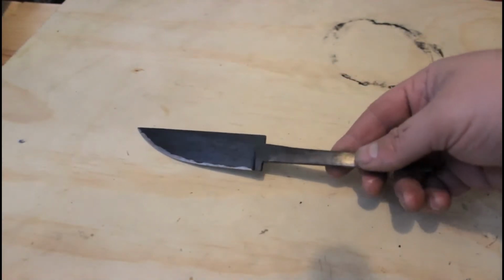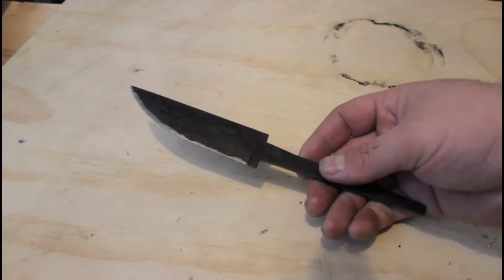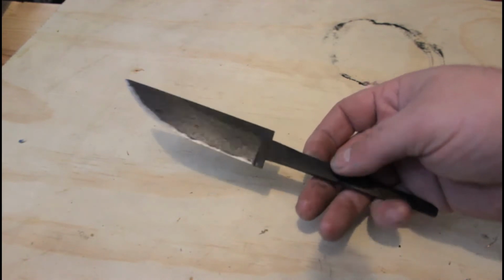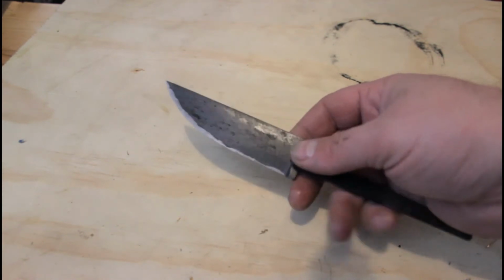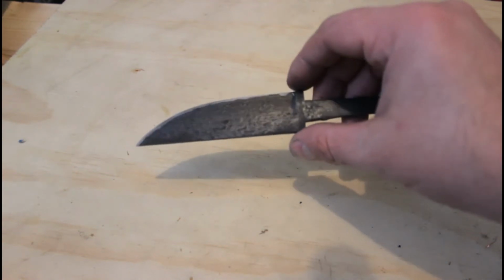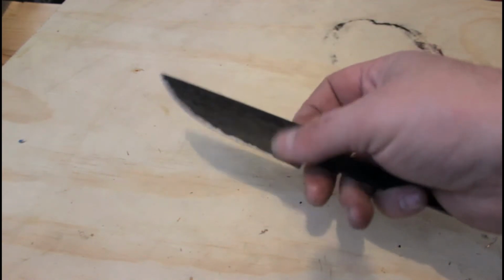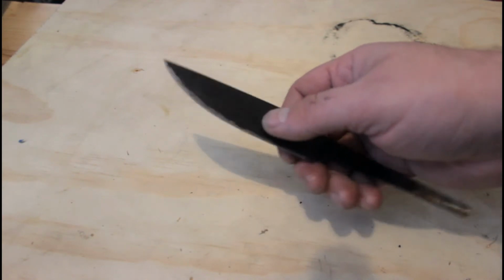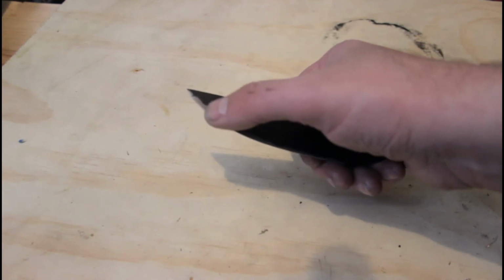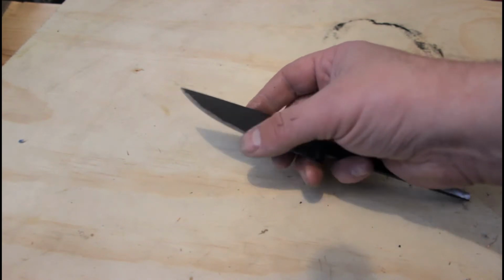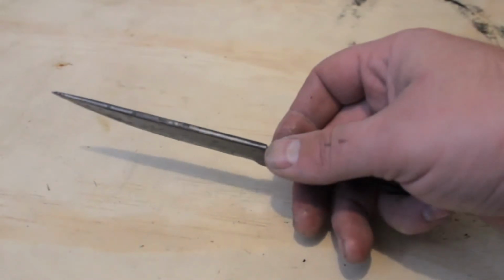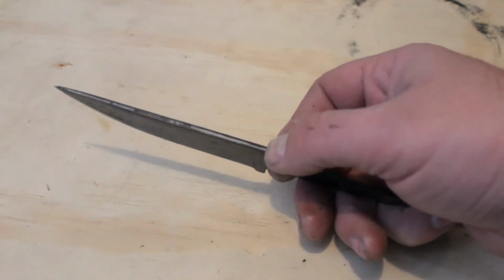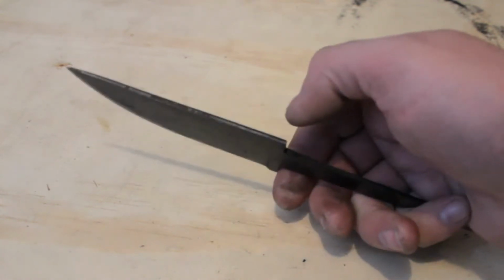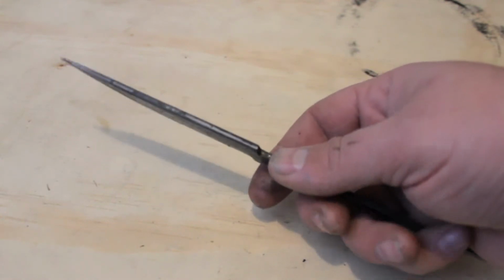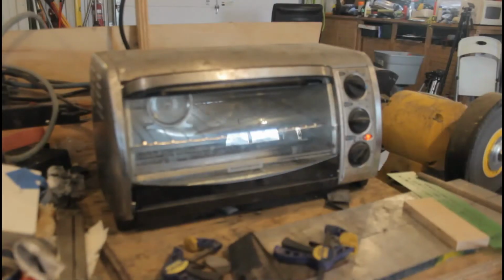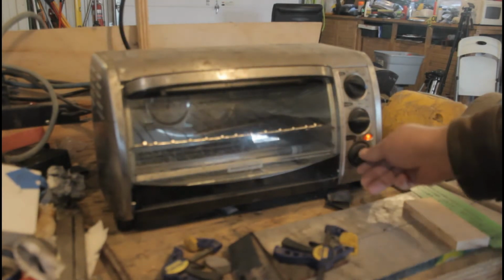So after the quench, we've got kind of an interesting result going on here. The stainless steel cladding is all crudded up and black with a thick coat of, I guess, baked on canola oil and scale and nasty stuff. But up here where the 52-100 high carbon edge is, it's actually pretty clean. And you can even see that on the spine. You can see the high carbon layer in the middle came out pretty clean, and the stainless on the outside is real cruddy. The next thing to do is get this knife tempered.